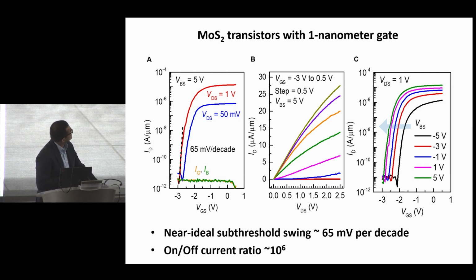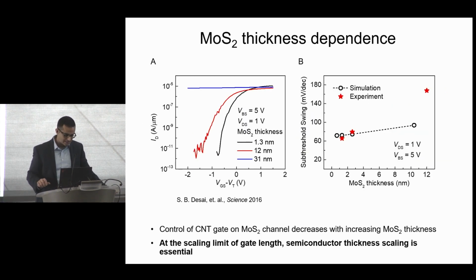And so these are the IV characteristics that we got. We were able to get about 65 millivolt per decade subthreshold swing. And these are pretty good transistors, granted that the current levels are very low. And the current levels are very low because the contacts and also those extension regions that we have were just simply acting as big parasitic resistors. So as a proof of concept, this shows that you can, in principle, make devices with physical gate lengths sub 4 nanometers, sub 5 nanometers, using these 2D semiconductors.